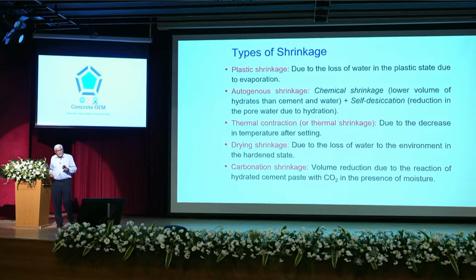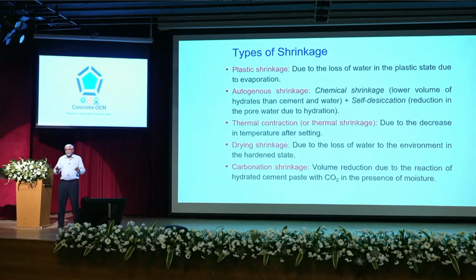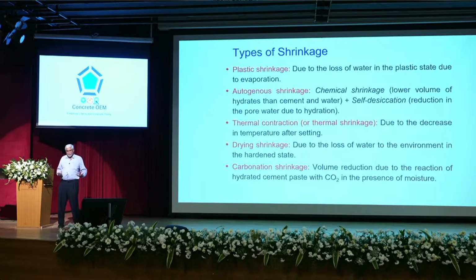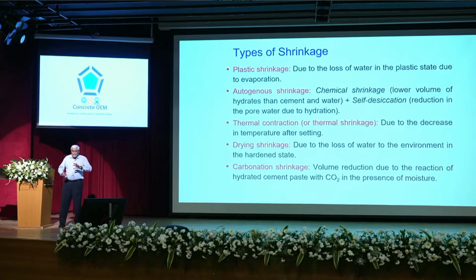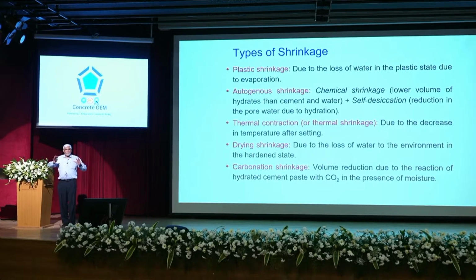I would like to focus on a few things which I believe are important to revise. I'll go through it fast. If you have doubts later, we'll go over it quickly. Cracking is of concern. Cracks sometimes happen fast, in a few weeks, months. Some cracks happen very much later. Now, shrinkage is a cause of concrete cracking when there is no load yet on the structure. If it happens very fast, when the concrete is still fresh, it is plastic shrinkage cracking due to the loss of water in the plastic state.